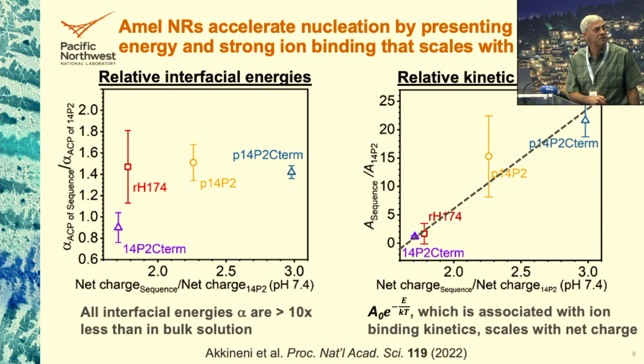If anything, it's worse. But when we look at the prefactor, what we find is that the prefactor scales with the net charge of the peptide or the protein. And because the phosphorylation sites are negatively charged sites, they lie at the top of this line, okay? And so it's the kinetic prefactor that's really driving the high nucleation rates on the phosphorylated nanoribbons.